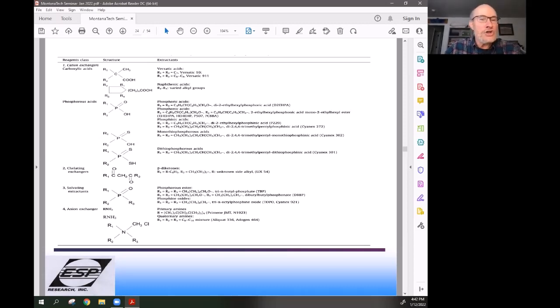And there are things like cation exchangers, which are primarily focused on carboxylic acids and/or phosphorus acids. They're functionalized in different ways in order to make them soluble in different solvents. There are diethyl phosphorus acids as well that take part in that. There are chelating exchangers such as the beta diketonates that are pretty effective for actually doing the chelation. And then there's solvating extractants such as the phosphorus ester materials that basically grab them and solvate them based on their polarities. And then there's anion exchangers based on primary amines.